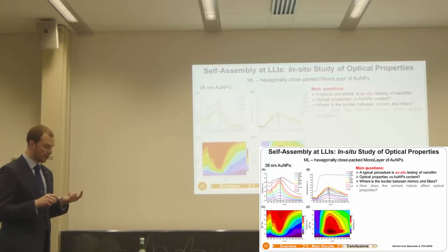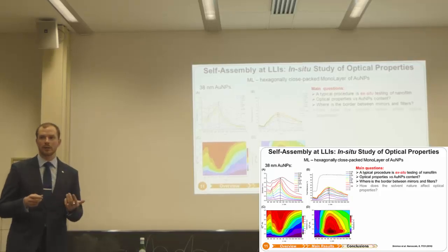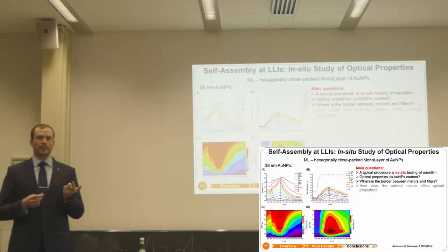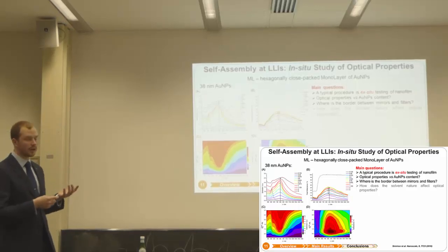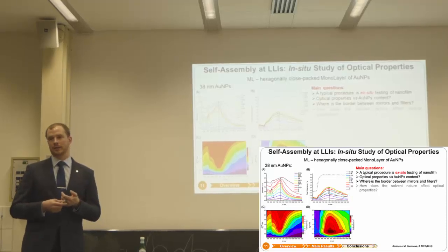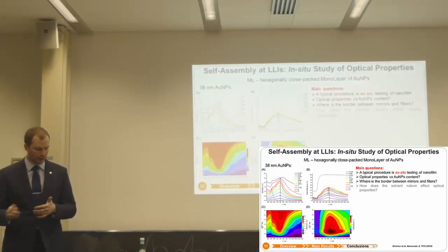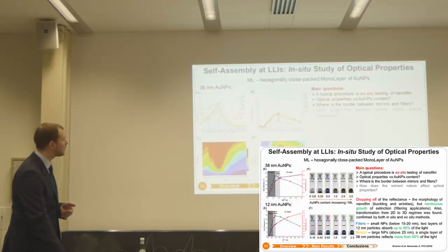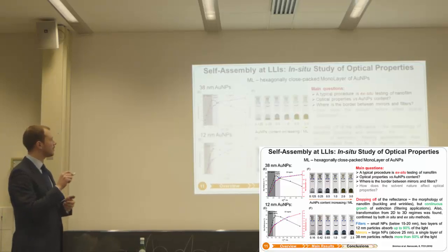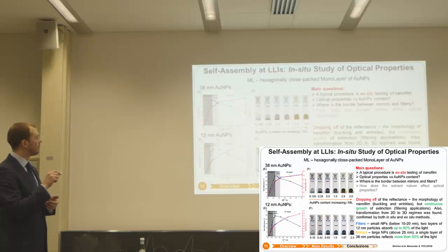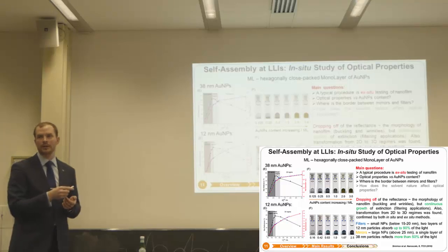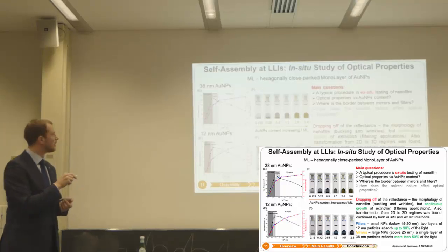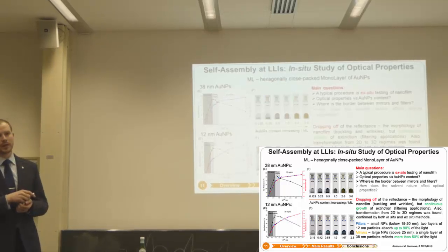But a more interesting question was how optical properties correlate with the gold nanoparticle content, because our mind and our thinking give us a clue that if we add more nanoparticles, we will have higher thickness, and then some saturation that corresponds to a polished gold mirror. However, it's not like that. If we plot it on a different scale, here the maximal reflectance versus coverage, we will clearly see that in the first region, it follows a linear line as our mind expects, but then it goes down,